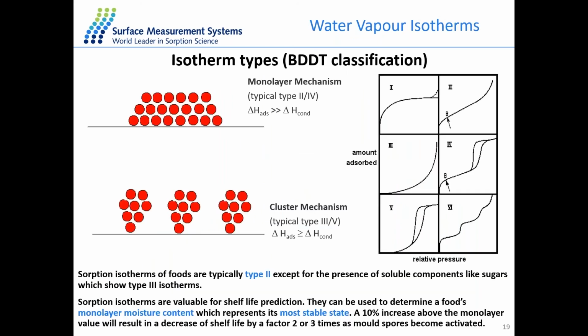So based on the classification, there are different types, 6 types of isotherm. Type 1 isotherm is typical for some microporous material. Type 2 and type 4 isotherms are typical for food samples, where the water molecule will interact with the surface, forming the monolayer first, and then it will further interact with the first layer to form multiple layers. And from the type 2 and type 4 isotherms, we can calculate the BET surface area of the material. The type 3 and type 5 isotherms are more like some condensation of the probe molecule on the surface, where the probe-probe interaction is too strong and will form clusters on the surface rather than cover the whole surface with the monolayer.